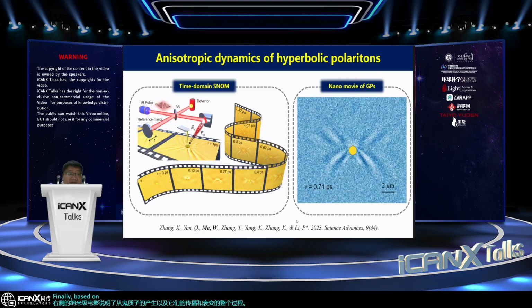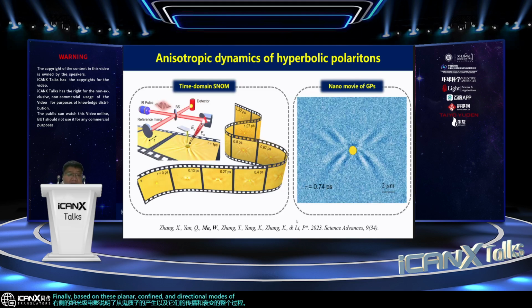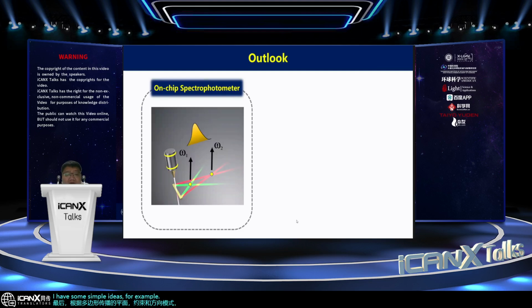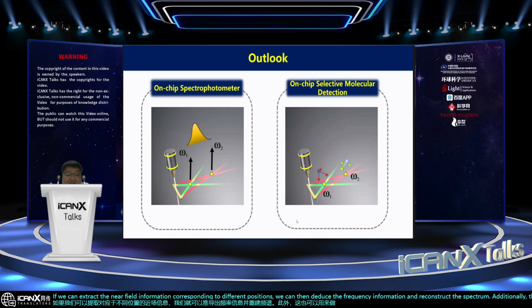Finally, based on these planar, confined, and directional modes of polariton propagation, I have some simple ideas. For example, if we have a linear optical antenna that can excite in-plane hyperbolic polariton propagation, the direction of the polariton and the incident frequency are strongly correlated. When polaritons are excited from the two apexes of the antenna, optical hotspots are formed at different positions for different frequencies. If we can extract the near-field information corresponding to different positions, we can then deduce the frequency information and reconstruct the spectrum. Additionally, this can also be used to identify different molecules at different positions.